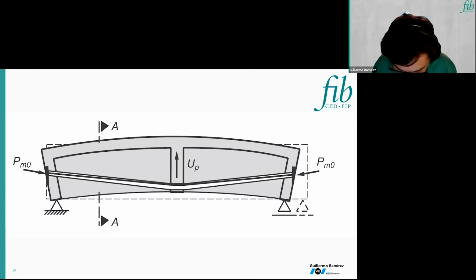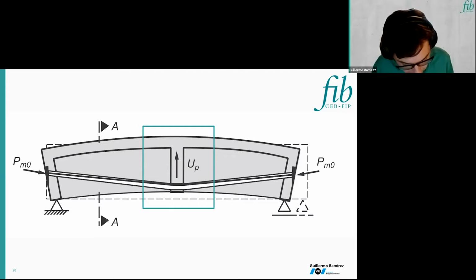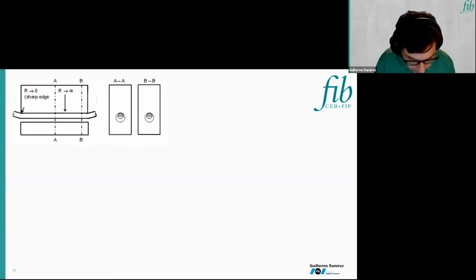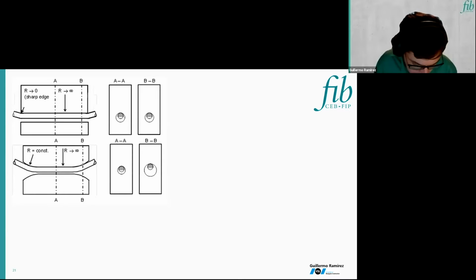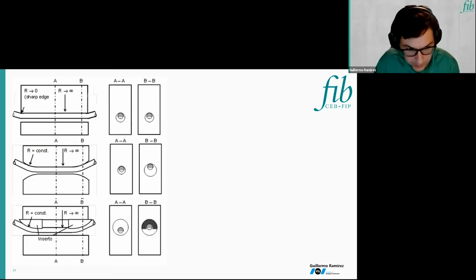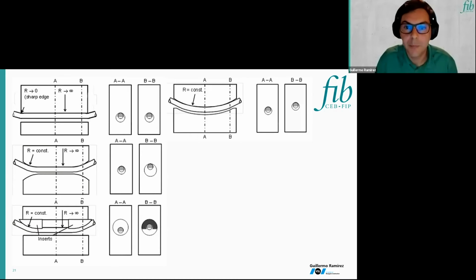In internal post-tensioning, the force is introduced continuously all along the length of the tendon. For external tendons, the uplift force is introduced through the deviators. Depending on the tendon layout and project requirements, a number of different solutions can be applied to deviate the tendon. We can have deviation around a sharp edge, which means radius close to 0. This is acceptable for deviations smaller than 2 degrees at both sides of the deviator. But for larger deviations, a positive constant radius is mandatory. These radii can be achieved with different solutions, whether it's making use of diabolos, using oversized pipes with the addition of inserts, or with pre-bent tubes.